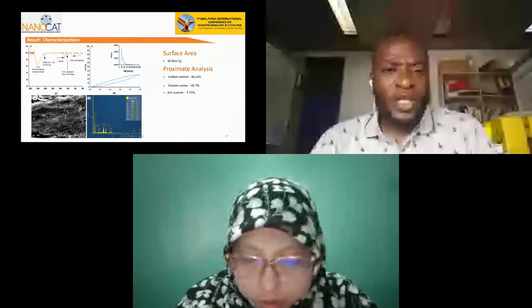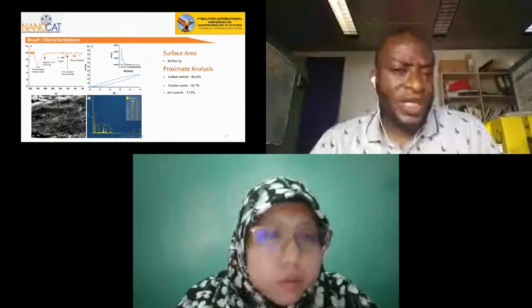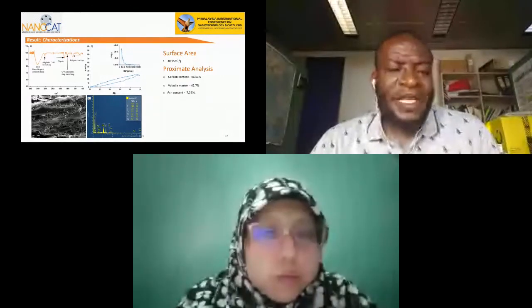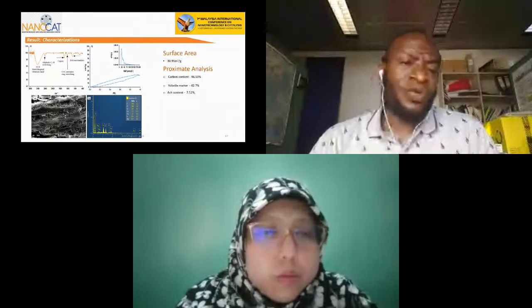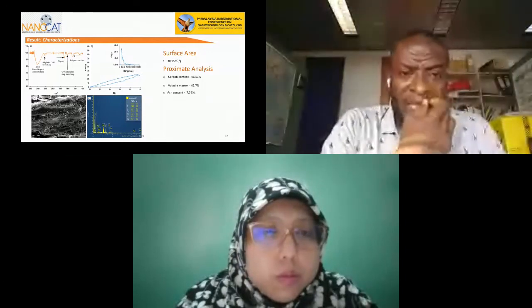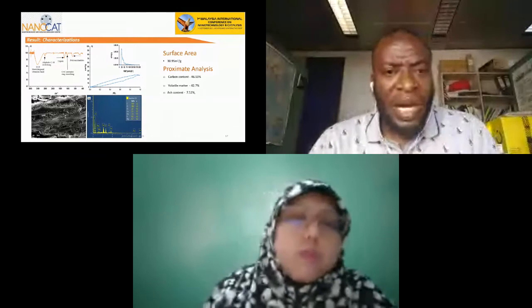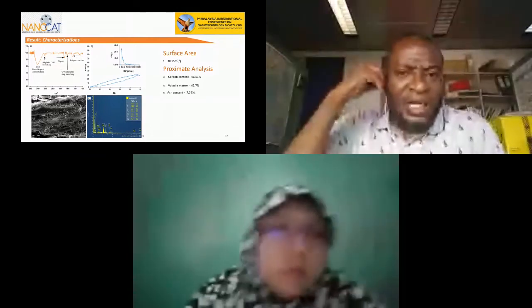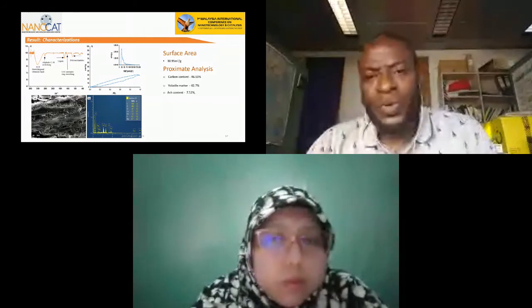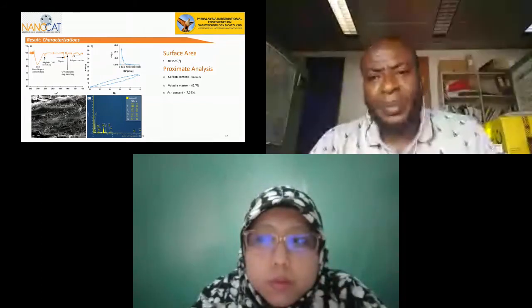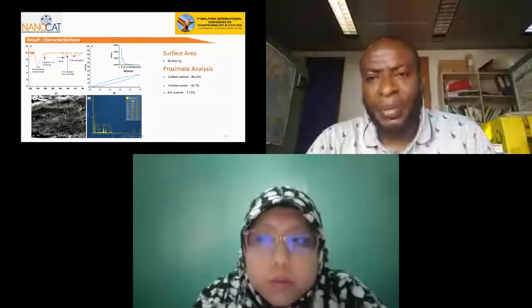And from the characterization, we do know that this is a biomass. It is not really treated. So we expect that there will be a number of functional groups on them, like OH, aromatic ring stretching, lignin, and aliphatic stretching. And from the surface area point of view, we found that it was around 30.95 meters square per gram.